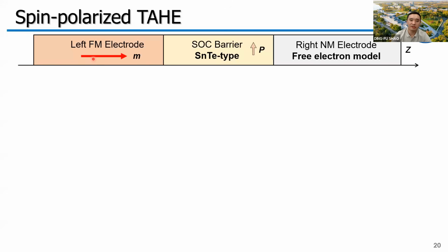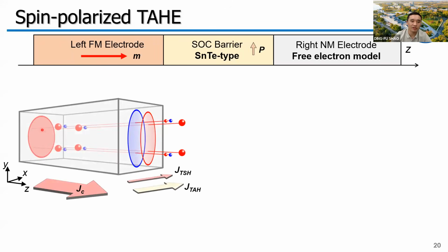Next, we change the left electrode to a ferromagnetic metal, where the Fermi surface is well spin polarized. In this case, longitudinal currents will carry mostly spin up electrons. We find in this case, the tunneling in this area is allowed, and in this area is largely blocked. This will generate an additional charge Hall current in this direction. So this effect is called the tunneling anomalous Hall effect.